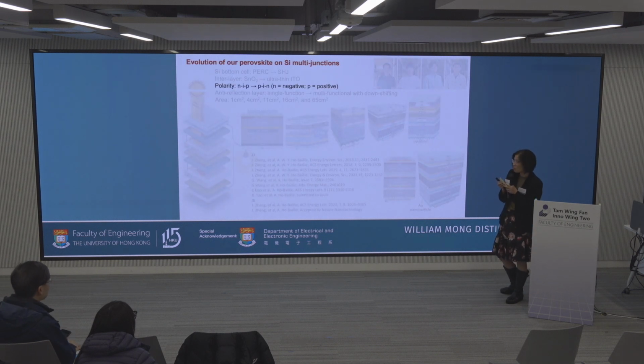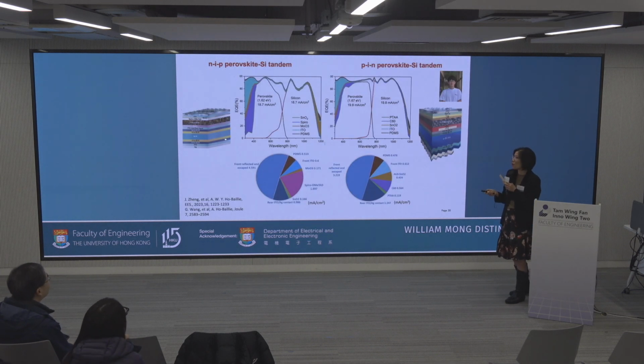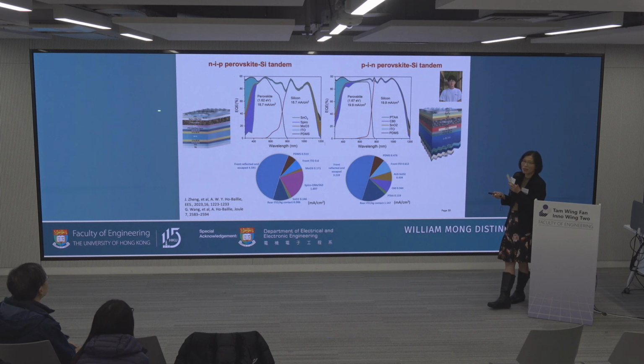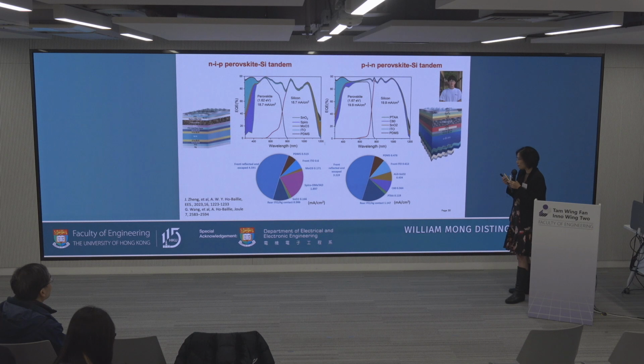Okay, so why do we move from NIP to PIN? It's because a lot of the hole transport layers are very absorptive. They absorb the sunlight, they steal the sunlight from the perovskite absorber, and it gets nowhere. It doesn't get converted to electrical energy, and therefore we call it parasitic absorption. So around 1.4 milliamps is being lost there. Whereas if you look at the PIN, the N stack, they're all very thin and they don't absorb as much sunlight. So through that, we can gain 1.2 milliamps per square centimeter.